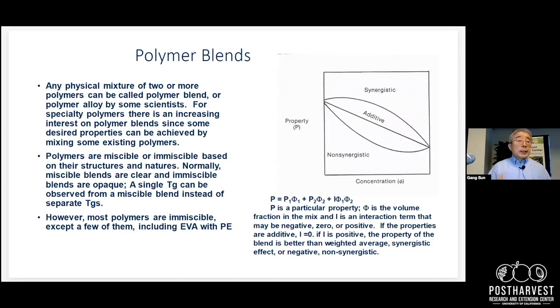But on the other side, as a material scientist, I also try to see that the polymers can be blended. It depends on the miscibility of the polymers, because the blend could provide good or bad properties. So I use synergistic and non-synergistic, or additive. Some of the polymer blends provide additive properties, so we can predict the property of your blend. That significantly drops the cost, bringing economic value, without losing the function. But if it's synergistic, even better, because mixing really provides very interesting phenomena, and economic and other performance benefits to the polymers, which is the reason nowadays you see a lot of films made this way.